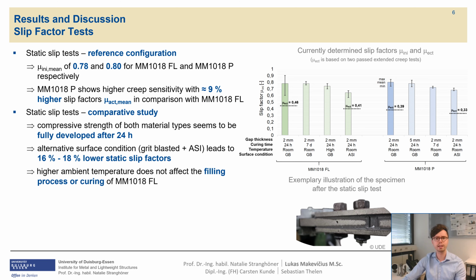The first comparative studies considering the static slip test confirmed that compressive strength of both material types seems to be fully developed after 24 hours. It can be seen though that an alternative surface condition, here grit blasted surfaces with alkali zinc silicate coating, leads to around 16 to 18% lower static slip factors. First investigations into variation of application temperature indicate that higher ambient temperature does not affect the filling process or curing of the liquid type of MM1018.